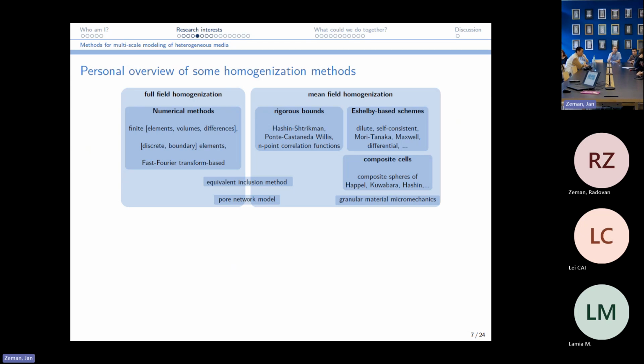So to compute the homogeneous properties from the microscopic scale, we have either full field homogenization, which would be to solve a boundary value problem on a representative volume element using your favorite numerical method, or you could do what's called mean field homogenization, in which you would try to estimate the microscopic response based on reasonable assumptions and simplifications. So either you can compute rigorous bounds to bound effective properties from above and from below, or you could do some estimates, which are usually based on the so-called Eshelby inclusion problem.